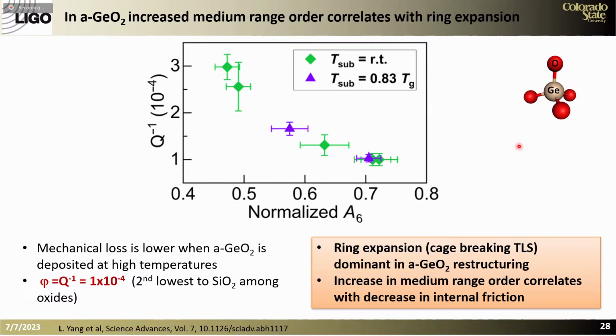So I mentioned at the beginning that we showed that in germania, when we grow the material at a temperature that is close to the glass transition temperature, we get a medium range order that is enhanced compared to depositing at temperatures of the order of 100 degrees C. Well, we carried out mechanical measurements on these films, and what we showed is that there is a correlation between the mechanical loss and the order. And this is shown here in this plot.